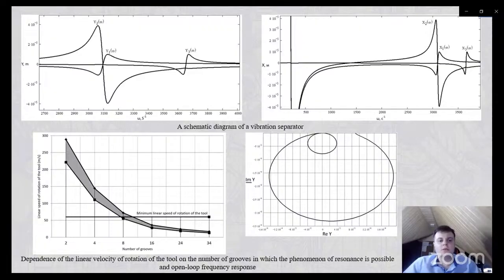The impact load frequencies were determined for a tool with a single groove on its work surface. In the article, it was investigated that under the thermodeformational treatment using a tool, high-frequency intense plastic deformation with a small amplitude occurs, and the article presented that high-frequency deformation positively affects the formation of a nanocrystalline layer. To determine the dangerous rotational velocity of the tool and the number of grooves on the disk periphery at which resonance can occur, a graphical dependence of the resonance on the number of grooves was constructed.